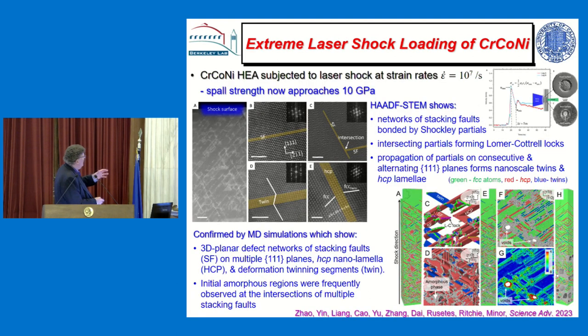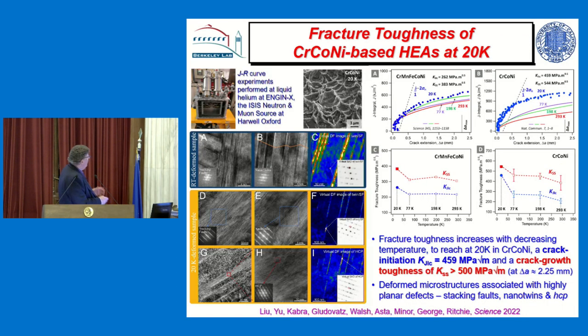We've done this with laser shock straining. We're now up to 10 to the 7, so we're about 10 orders of magnitude faster. And we see all these interesting deformation mechanisms which generate strength and ductility. We've even gone to liquid helium temperatures, and we've seen the same thing. We get these planar slip bands, we get forming of what's called stacking faults, we get twinning, we get the formation of another phase.